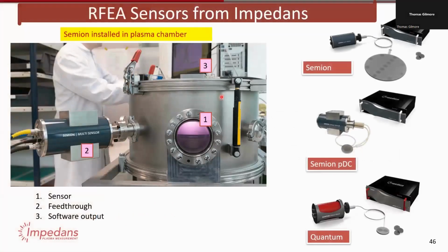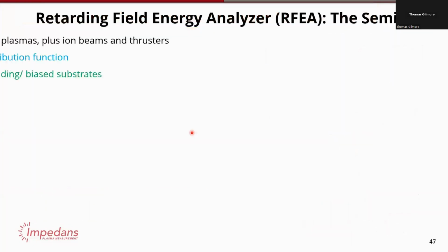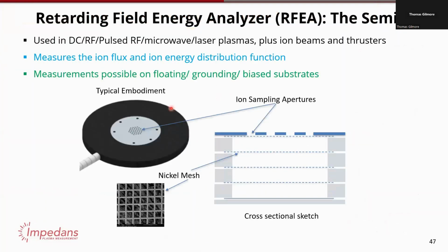You may be familiar that Impedans has these RFEAs, the Semion, Semion PDC, Quantum, and other things. And this is how you install one on the tool. You can see an ion energy analyzer in the tool here. You can see this is the vacuum feedthrough, and you see the data in the background. I think many people on this call are familiar with what we have. And this is sort of a cross section of the sensor. You have these nickel meshes, you have various different grids. We apply different voltages to them in order to discriminate the ion energies. And then by measuring the current and the transmission of all this, we can get the ion flux.